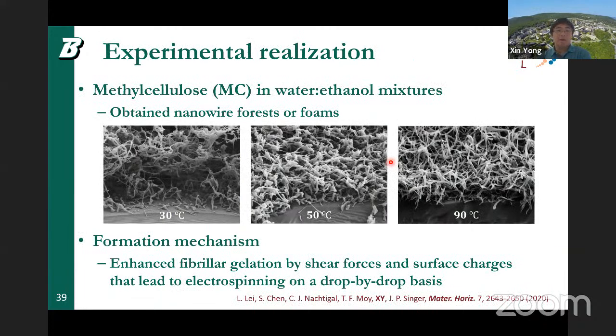And so we realized this experiment with our collaborators at Rutgers, who found this particular material, methylcellulose, in a water-ethanol mixture. If we spray it, we can lead to this gelation where we obtain this nanowire forest. So these are higher-order three-dimensional structures of the individual nanowires that we see similarly in our simulation prediction. We still do not fully understand the formation mechanism here for this rapid homogeneous viscosity increase, but we believe it's due to the enhanced fibrillar gelation under the extreme shear and surface charge. So effectively, the individual droplet electrospins. You can think of it that way under these conditions.